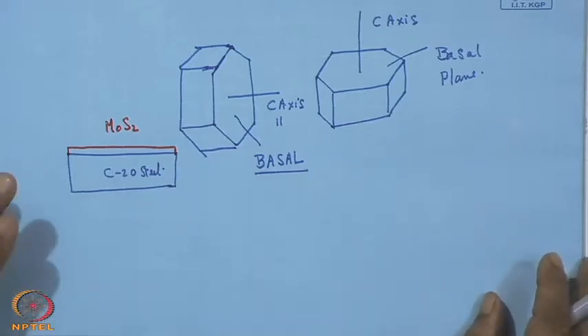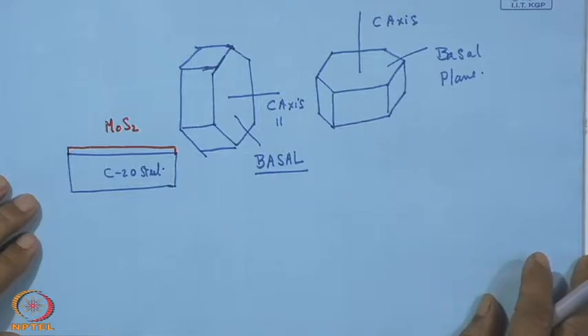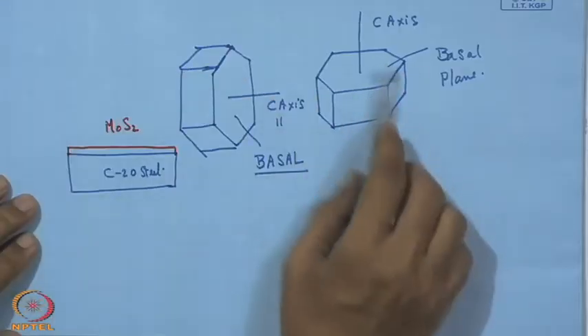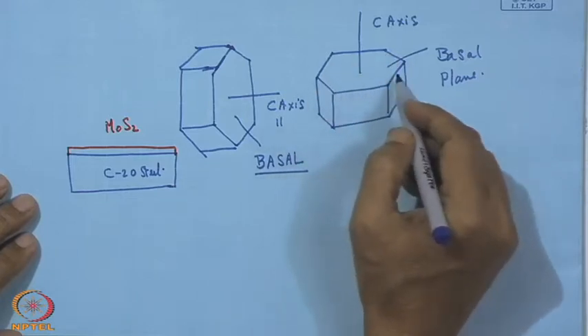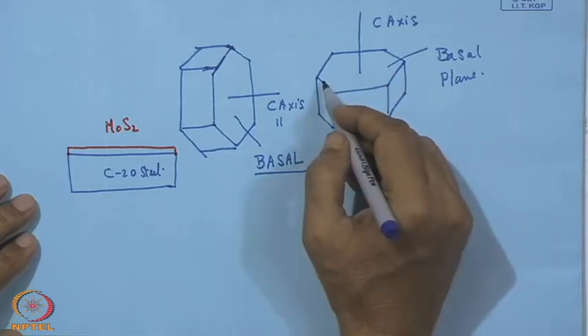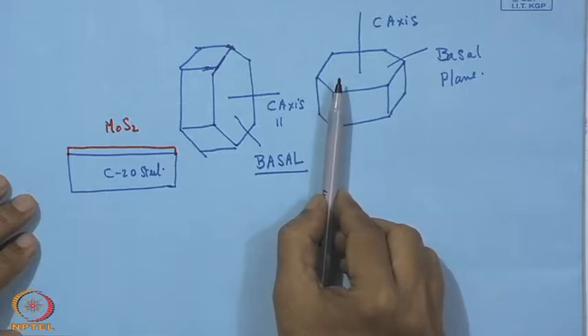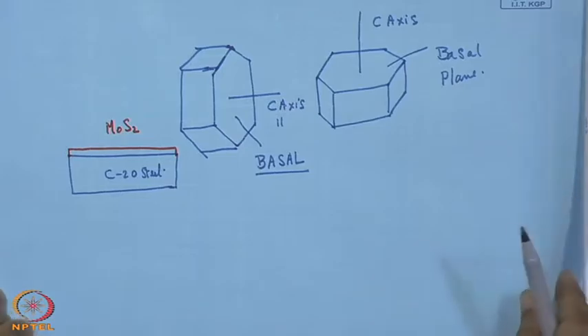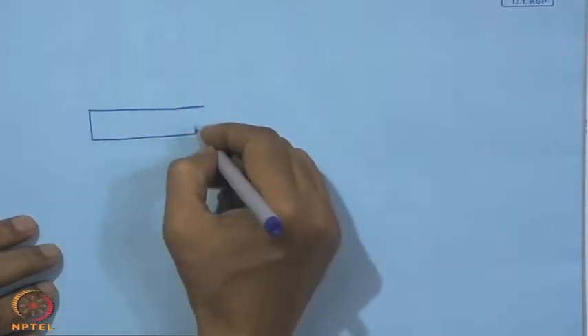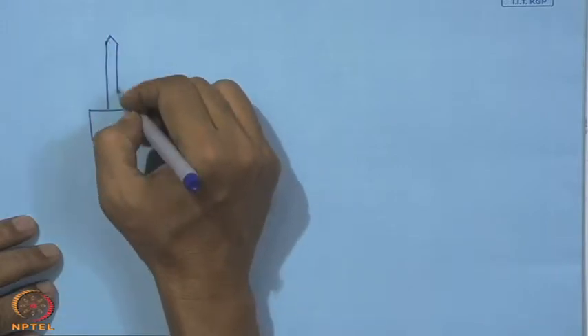Now, here we can summarize one thing, that even to have this coating, whether it is PVD or any other process, first and foremost is whether this basal plane is parallel to the substrate surface, because only in this direction, as it slides here, can we expect a good coefficient of friction. And if it is perpendicular like this, then this sliding will not be easy, rather sliding will be difficult, with the result of high value of friction, high sliding force and removal of the coating. Another thing also we can look at here, that this normal orientation, say we have the substrate here, and these are the arrays of coating.